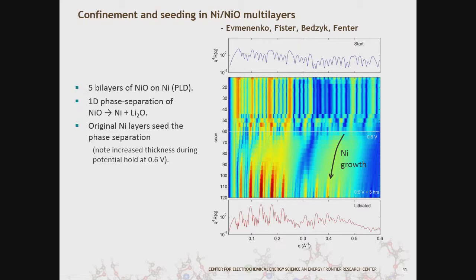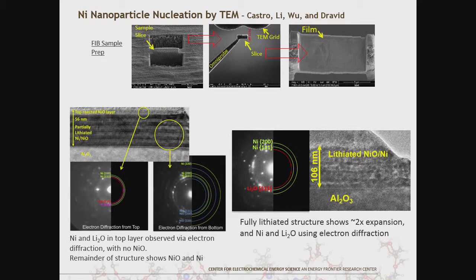Again, we have this conversion reaction, so the nickel is acting as a sink for the lithium in the reaction. After we let it sit for a while, the multilayer reforms, and all the layers start to order up again. So this is showing that we can control this reaction through this process.